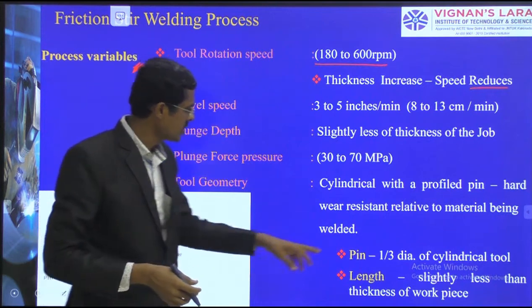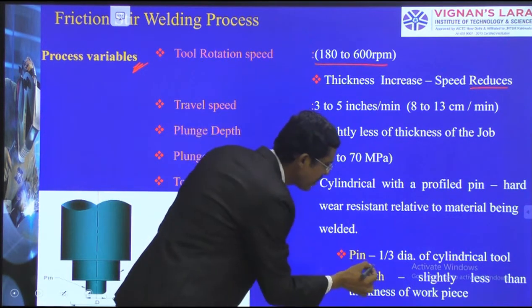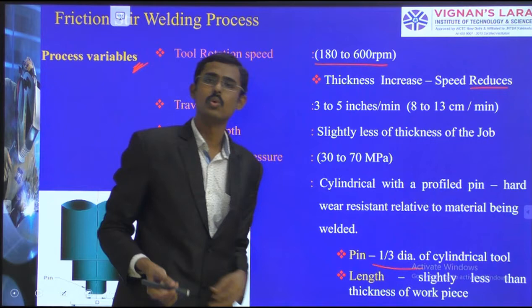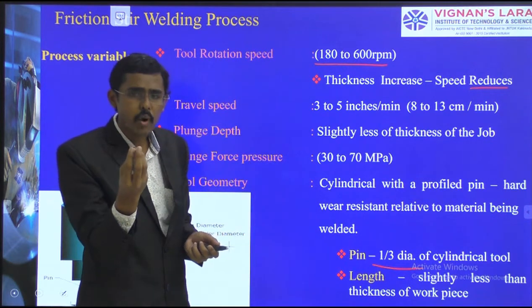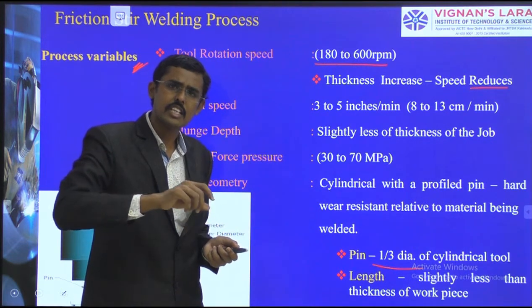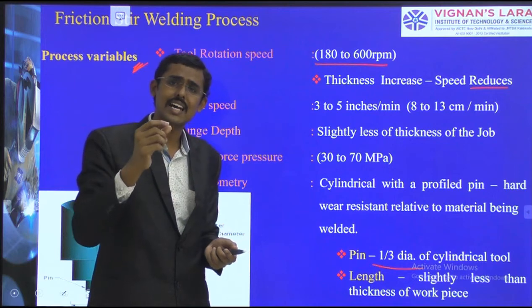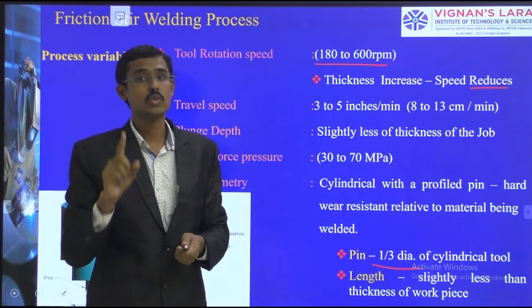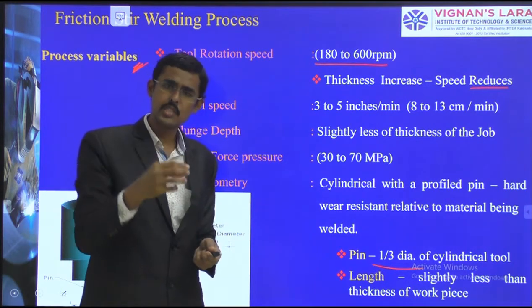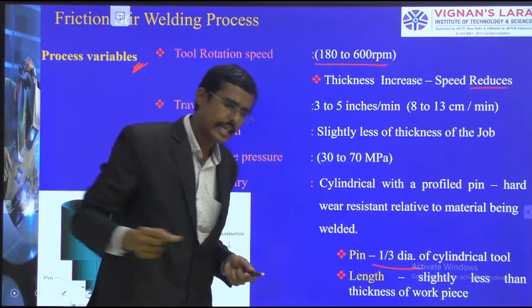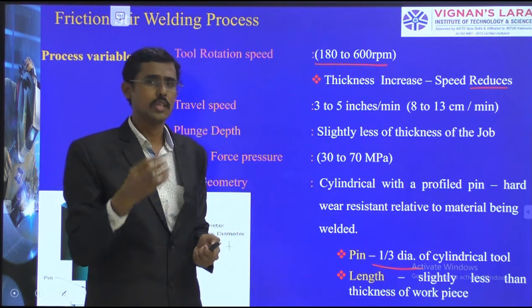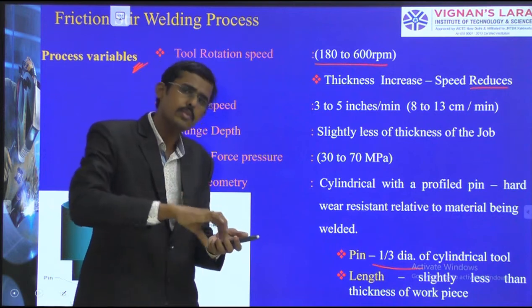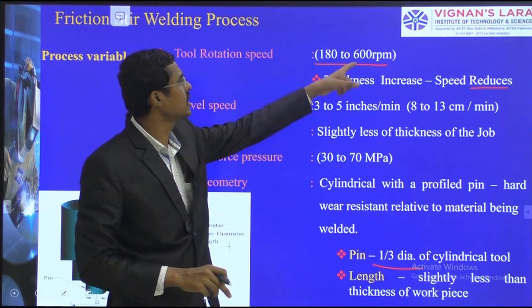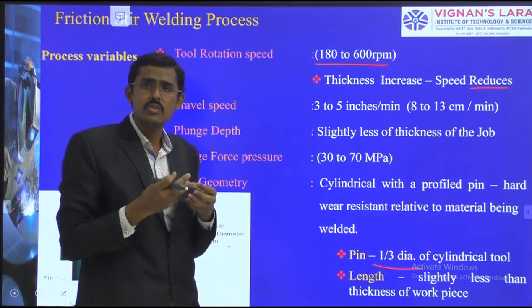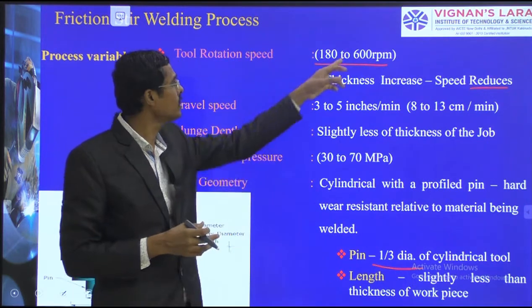Therefore, see, the pin is equal to 1/3 of the diameter of the cylindrical tool. This tool is a very pinpoint. If you rotate very fast at the hard point, the pin, there is a chance it will break. It should not break. With a small pin, the entire heating occurs. Therefore, we should carefully handle the rotation. 600 rpm is huge. We should use it for lower thicknesses.